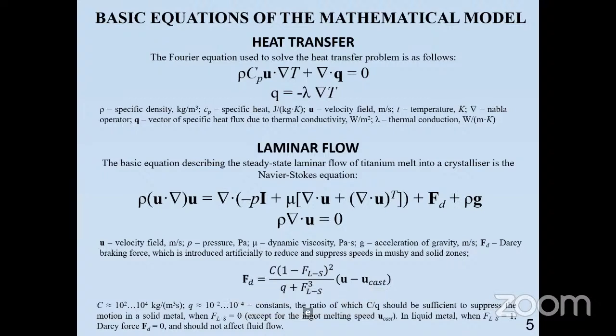The calculation of hydrodynamic processes that occur during the continuous casting of titanium alloy into the crystallizer was based on the following assumptions. Liquid metal is poured into the crystallizer continuously at some speed. A constant ingot extraction speed is ensured. The mirror of the melt pool is a flat surface. The melt was considered a viscous, incompressible liquid. The movement was assumed to be laminar.